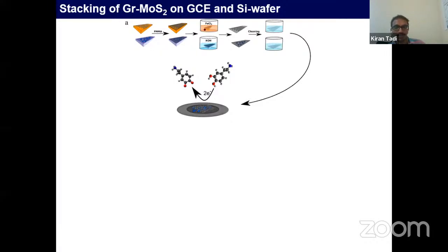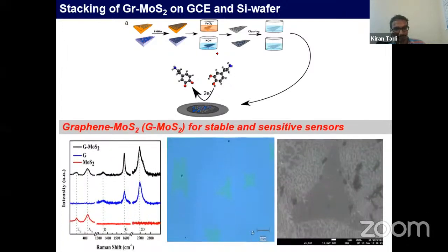It is somewhat difficult, and we need to be careful because this is a single atomic thickness layer we are dealing with. Once prepared, graphene and MoS2 peaks are characterized using Raman spectroscopy, which simultaneously confirms graphene on the MoS2 layer. This star contains a MoS2 structure, and graphene is deposited on it in this case.